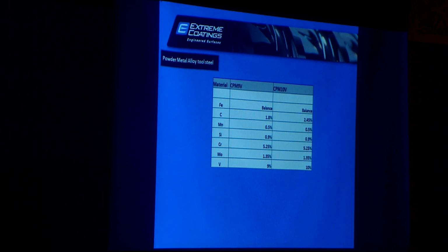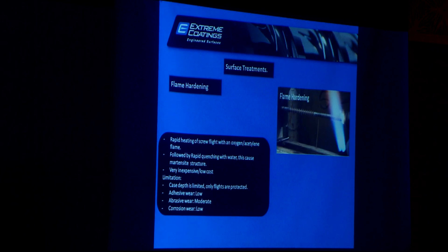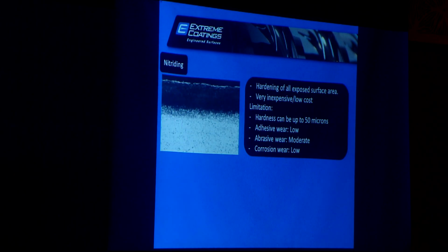So what I'm trying to say here is that when you purchase a steel, you have a very limited scope with adding elements which can improve the property of the steel. And that's why extra treatment needs to be done. What are the extra treatments we can do? Flame hardening. This is very common. I will not go into this. Nitriding is also very common. You have a steel, you put it in the nitriding tank for a certain period of time, and nitrogen penetrates inside the steel surface. So what it does, it creates a 40 or 50 microns hard layer.